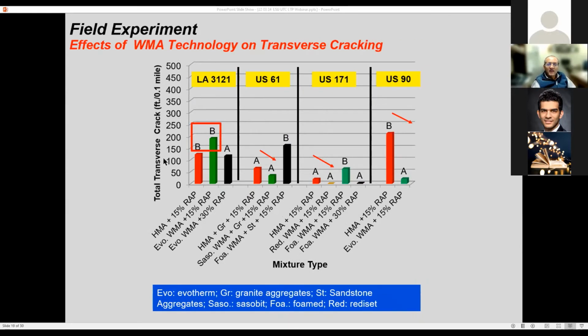Looking at transverse cracking in this particular slide from field performance, one would observe that the HMA and the WMA, most of them were statistically similar. They might be slightly higher in number, but they were statistically similar. It's interesting that the 30% RAP had slightly lower transverse cracking. And again, this could be issues related to what's going on underneath. Right here, you see what's expected in the US 90: the 15% RAP mixture did extremely well in crack resistance as compared to the counterpart HMA mixture.